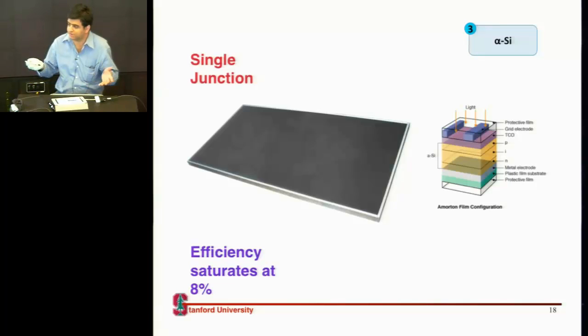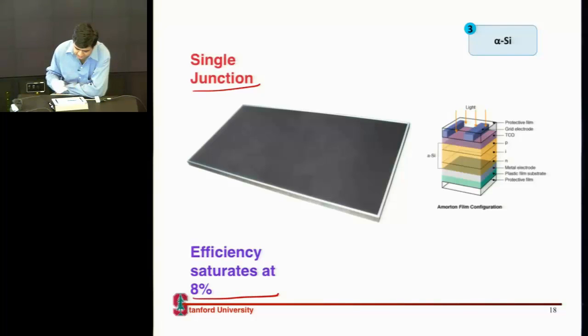So it's an amorphous material, right? So there are so many of these dangling bonds, these tail states. So a lot more of what you absorb, you only collect as current a very small fraction of that. So the efficiencies of these single junction cells made out of amorphous silicon, they saturate at around 8%.